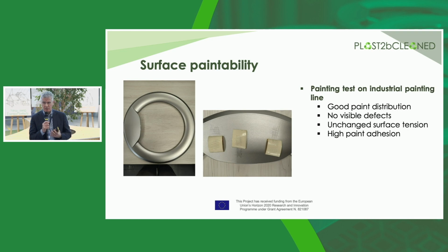Another key part for us is also the possibility to paint that frame. We have some versions, some appliances where we apply a wet paint on the surface, and the characteristic of the surface needs to fulfill some requirements. And the good point was that the distribution of the paint was good. Again, no defects on the paint because the surface tension of the material was unchanged.